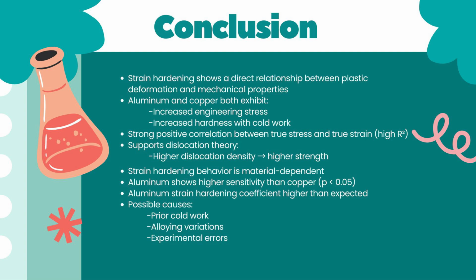Aluminum and copper both exhibit increased engineering stress and increased hardness with cold work. Strong positive correlation between true stress and true strain with high R-squared value supports dislocation theory. Higher dislocation density equals higher strength. Strain hardening behavior is material dependent. Aluminum shows higher sensitivity than copper. Aluminum strain hardening coefficient is higher than expected. Possible causes are prior cold work, alloying variation, and experimental errors.